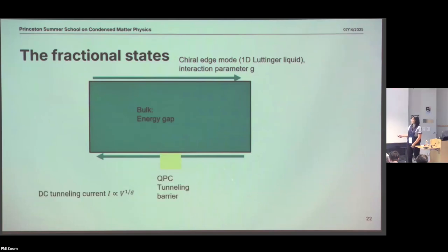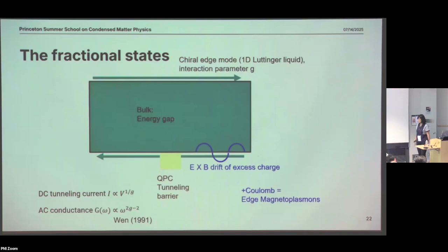Well, you might know the result that if you have a quantum point contact and a tunneling barrier, then when you measure the tunneling current through that barrier, this current has some power law relationship with this interaction parameter. But in the AC field, there's actually another dependence, which was also proposed by Wen in the 1990s or so. The AC conductivity has a frequency dependence that goes as omega to the 2g minus 2. So this is another type of power law relationship that may be helpful for understanding this type of fractional states. But more than that, what happens on the edge is you have some electric fields and magnetic fields now perpendicular to each other, and classically that would just induce charge drift.